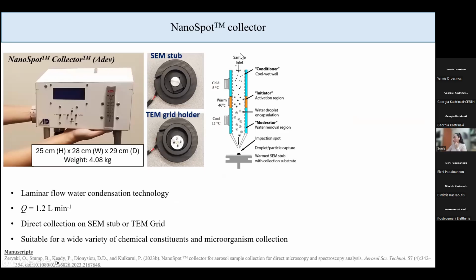First, we have the aerosol flowing through 3 different stages. First, it flows through a cold stage, the conditioner, which cools the aerosol flow and humidifies it. Then it flows through the initiator stage, where the wick that surrounds the aerosol is heated to high temperatures, releasing vapor across the radial axis of the aerosol stream. And then because the vapor diffuses faster across the radial axis than heat does, we have generation of supersaturation, vapor activation on the surface of the particulates, and subsequent droplet growth.